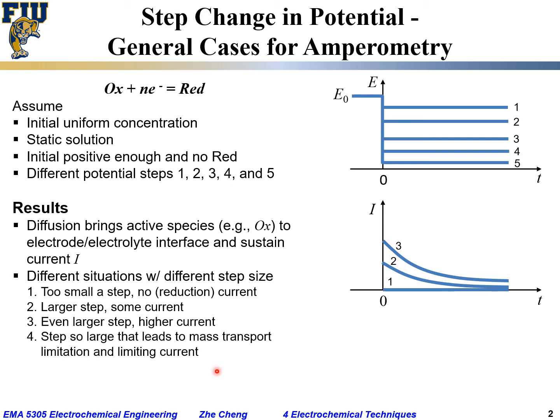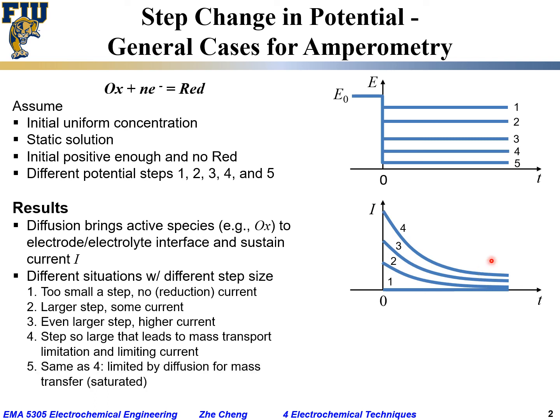And for situation four, the potential step is large enough, or in this case, negative enough, that it directly lands in the mass transfer limited zone, mass transport limitation. It starts from the highest current possible and then starts to decrease. Okay, and then finally, if you go beyond four, go to five, it is an even larger step, even more negative than 4, but because it's already limited by the mass transport limitation, the current cannot go any larger. So for both 4 and 5, we will have the same current profile with time. Okay? So this gives us the situation. For different potential steps, we would have different current profiles with time.